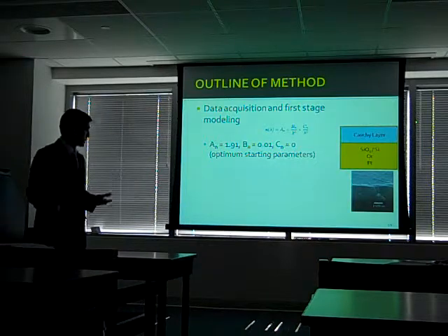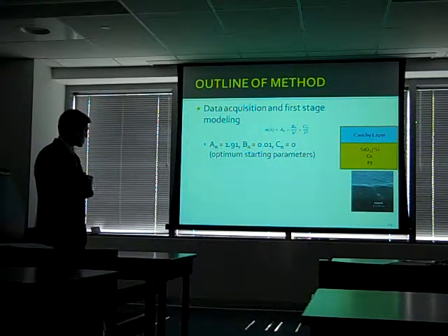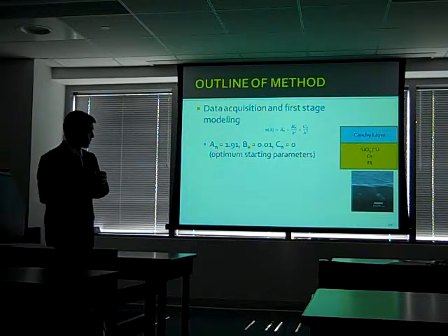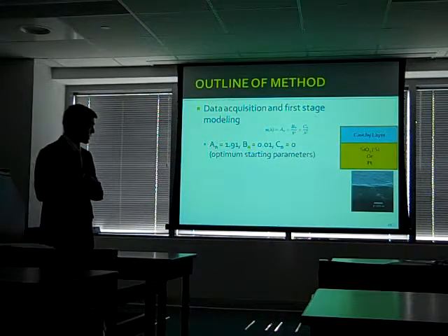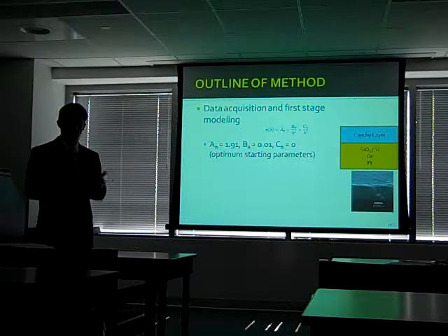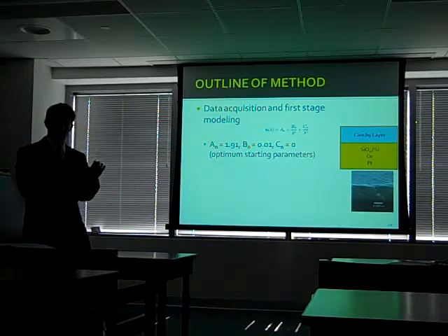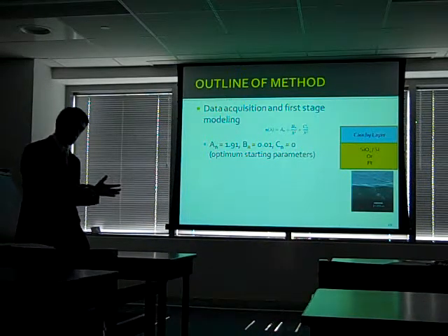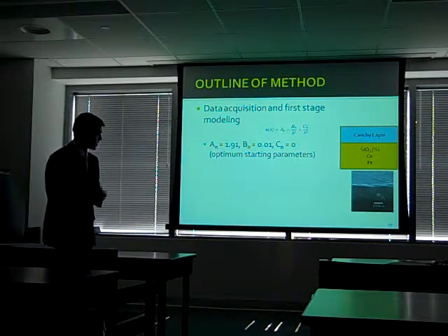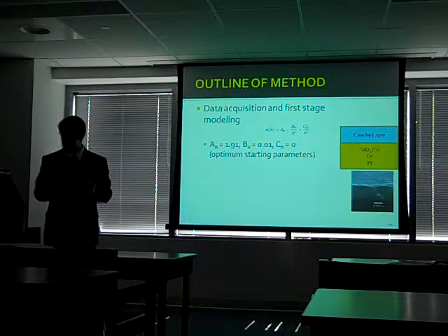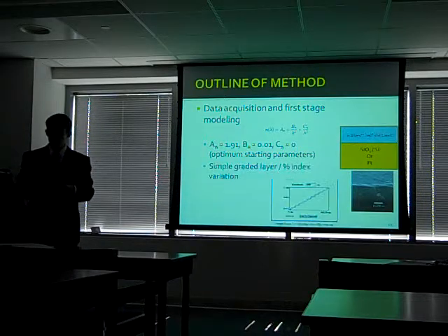Based on my work, I've come up with these optimum starting parameters, and then for the thickness, the best way to start is you start with 100 nanometers and slowly increase the thickness in the model until the calculated delta roughly lines up with the experimental delta. And then from there you can run the model and get a best fit.